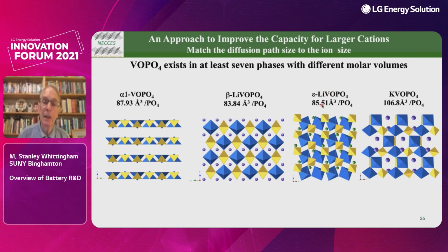These two are equally good for lithium. There doesn't seem to be too much difference. And there's this potassium phase, which is much larger. And we found this phase will readily intercalate sodium in and out. Sodium does not easily go into these lattices. It's too large for the tunnel size. But this one will go into it. If we take the potassium out, we can then put sodium into the lattice.